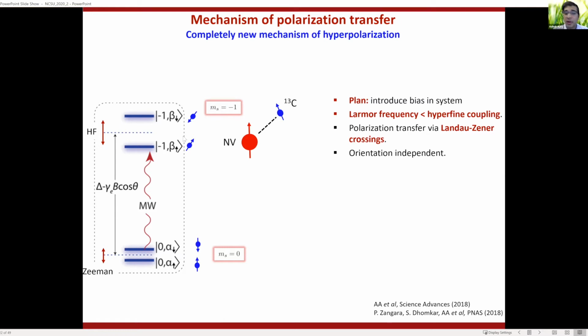So when you shine laser on the system, all the NV spins are polarized to this manifold. So you don't have any population here. You only have population here. But between these two levels, which are very close in energy, they have almost equal population, to within a part per trillion or so. So there's no population difference between them. But you can hyperpolarize the system if you can introduce bias. So you want one of the spin states to go in a different path compared to the other. And if you can do this, then you can somehow set up bias so that all the population travels to one of the spin states and not the other.